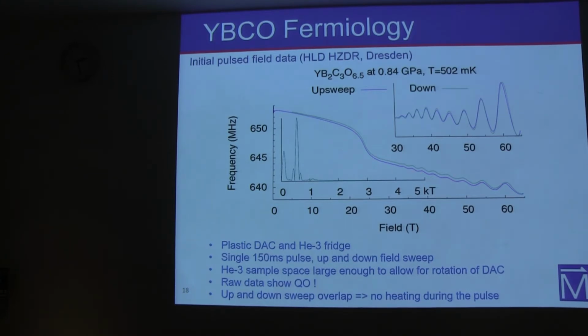The fact that those two curves overlap perfectly means that by using completely plastic technology of cryostats and pressure cells, we do not generate any heat during the pulse. And for us, it's really important. The small shift is very tiny, and if you compare with other experiments, other people working in pulsed field will show you only the upsweep. If somebody does not show you the downsweep, it means that there is heating and you don't see the oscillations, or you have a straight curve that does not fall back to itself. So this small shift is actually not that much. There is actually no heating.